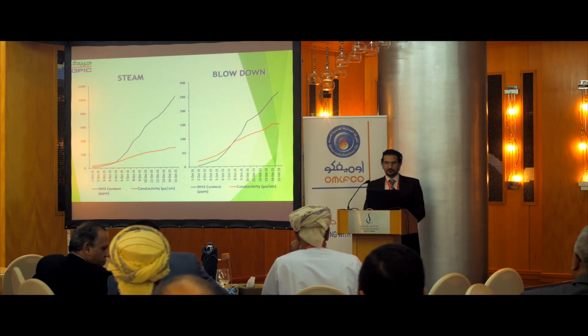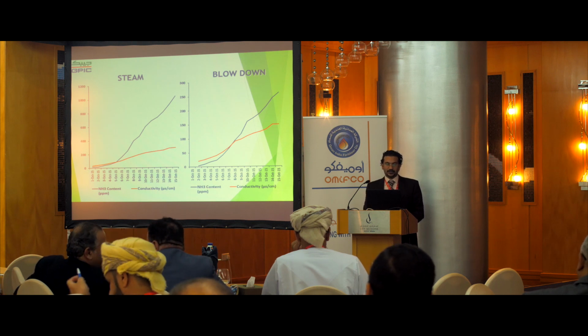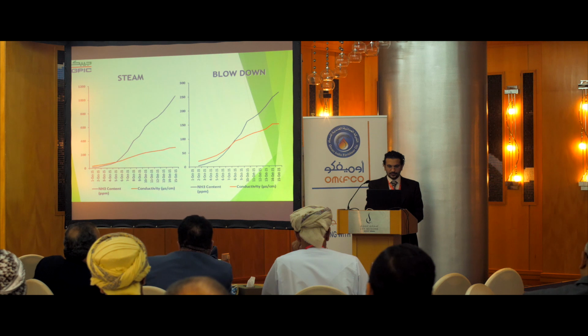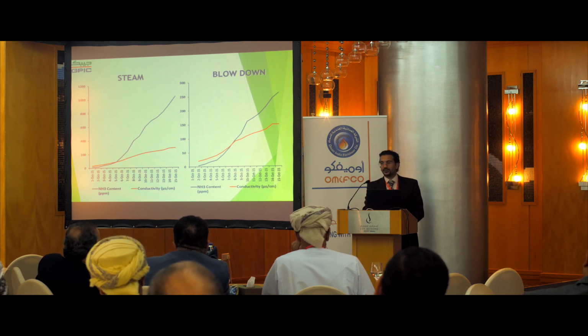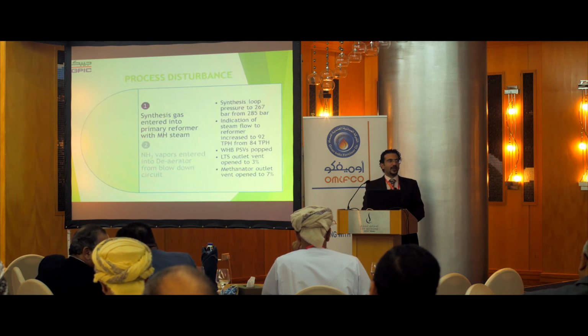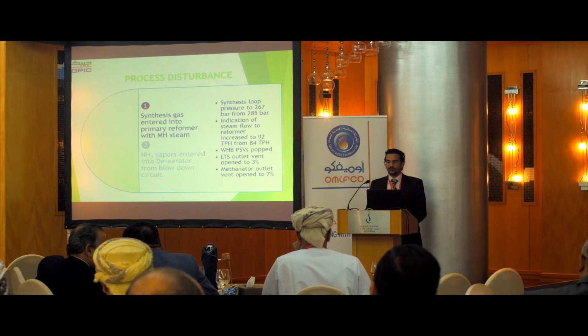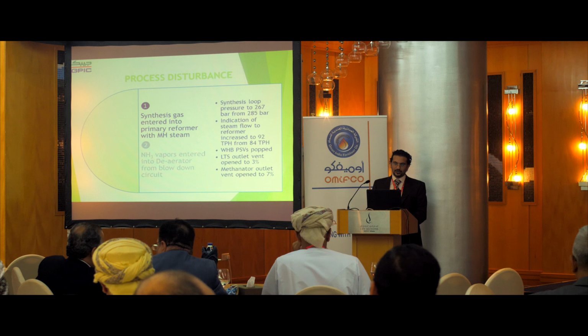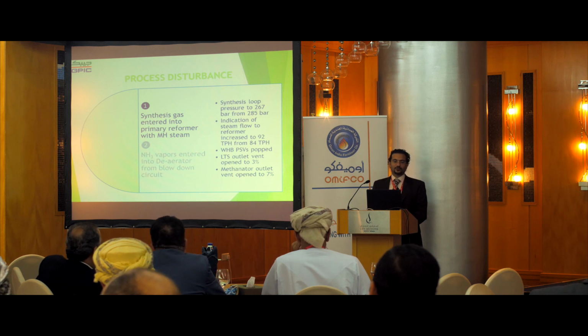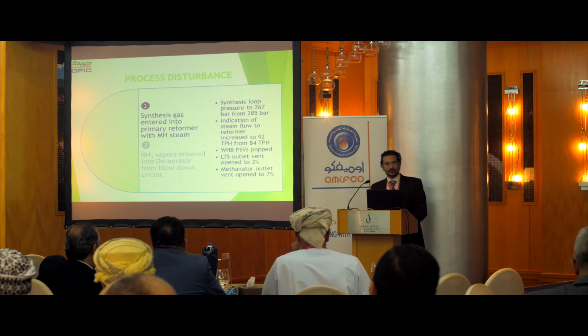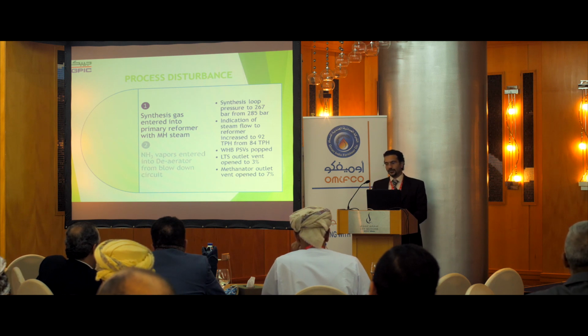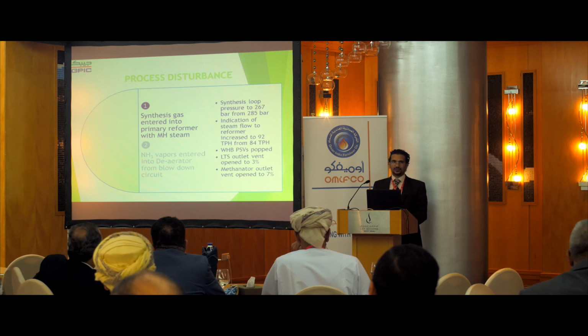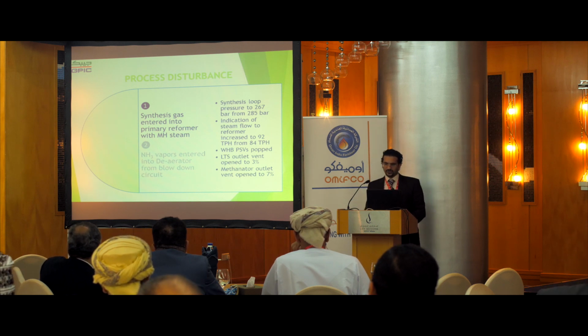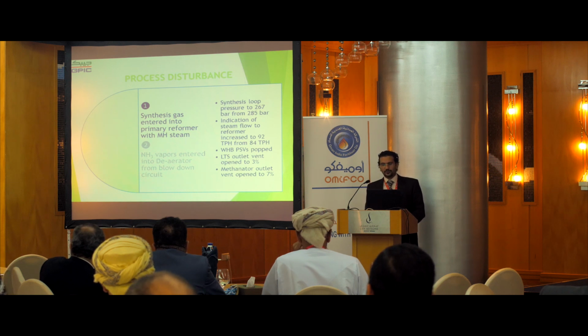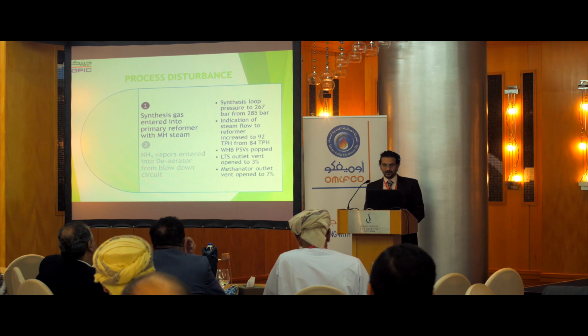So this is the steam and the blowdown conductivity and ammonia content over the two weeks, and how it increased drastically throughout the weeks. When the failure happened, it disturbed our plant steam a lot. Synthesis gas entered the primary reformer with the MP steam. The loop pressure decreased drastically by about 20 bar, from 285 to 267. Indication of the steam flow to the reformer increased by almost 9 tons.